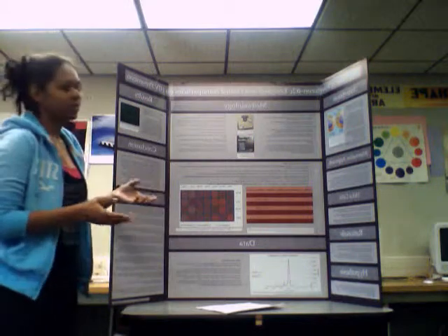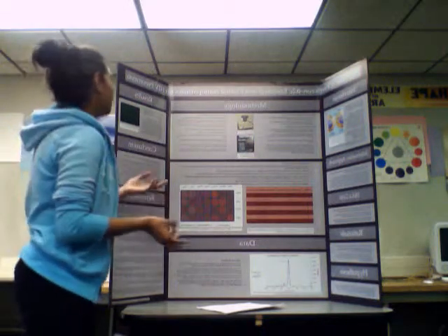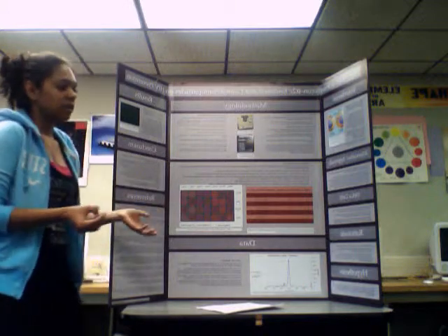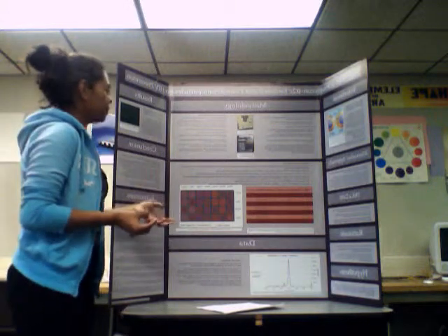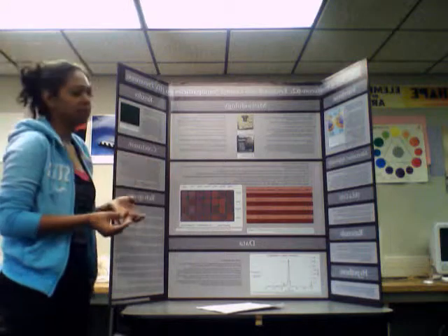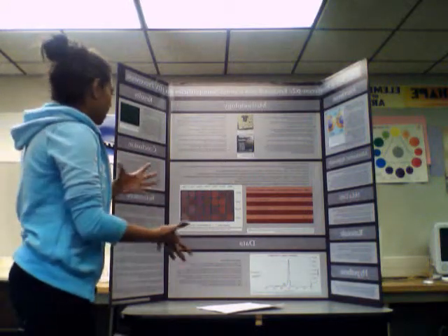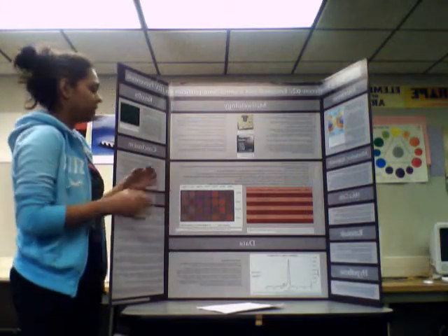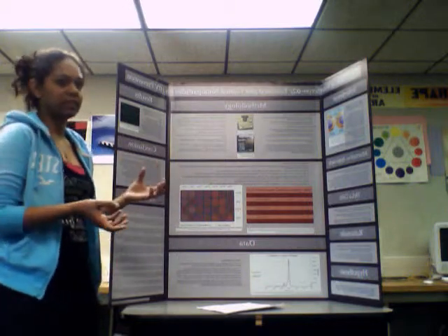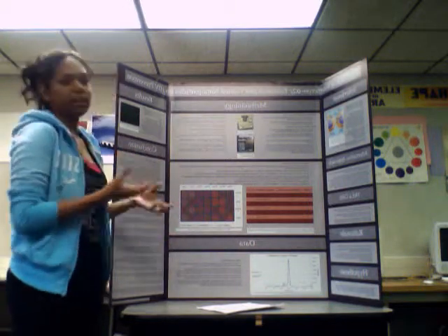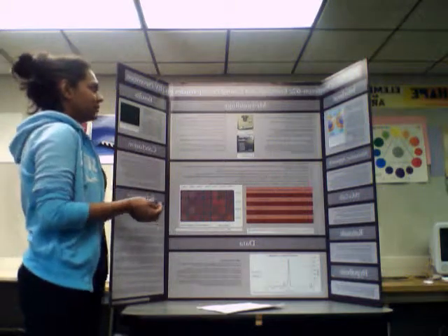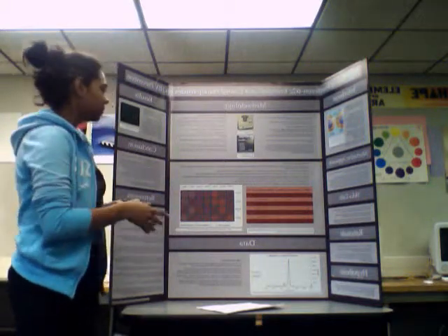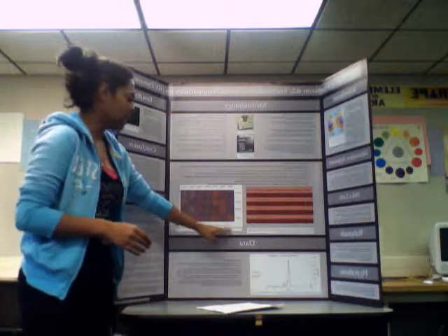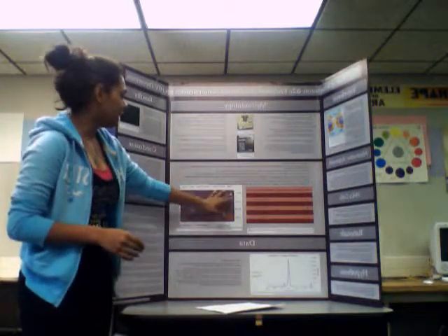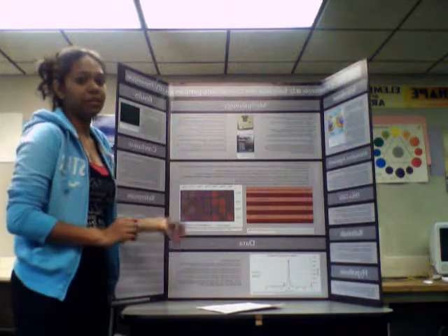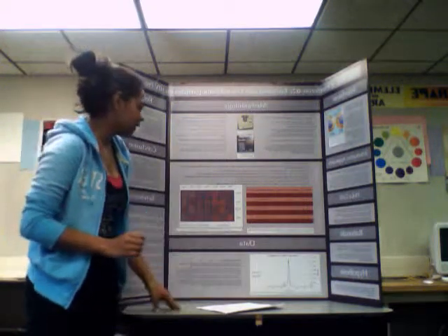As for the results, they show that the interferon pre-treatment had no effect on the HIV samples. So this shows that there may have been some inconsistencies. First of all, there may have been problems with the surface receptor of the HeLa cells. Maybe it did not recognize the interferon cell receptor. Also, what I observed was that in the higher concentration sample, most of the cells were very weak but not dead, and there were also signs of contamination.